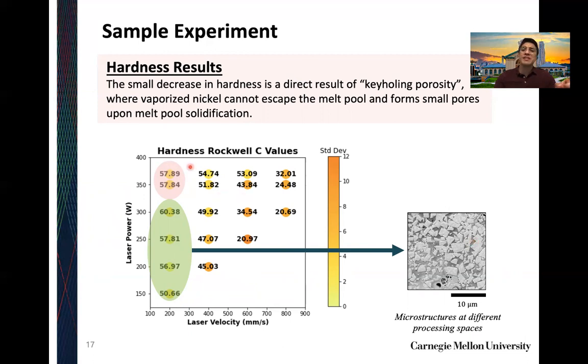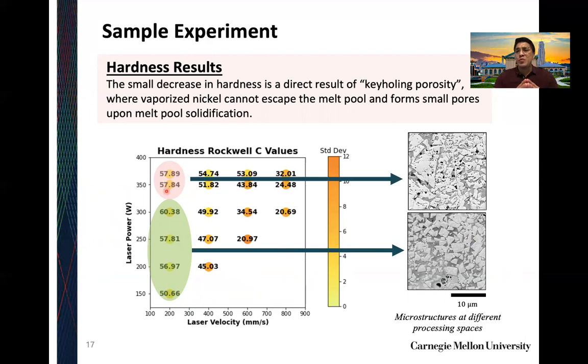But what was very interesting is looking at these top two specimens, we see that the nickel phase actually has a lot of pores. They're micropores, smaller than 1 micron, so they're very small, but they're pores nonetheless. And we realized that they're in the nickel phase. So we hypothesize that at these higher powers, we're causing our nickel matrix or nickel binder to vaporize, and that gaseous metal induces a vapor pocket within our material. And because of the high resolidification rates, we are resolidifying with vapor pockets inside. And that's what causes the decrease in the mechanical integrity or hardness of our samples.